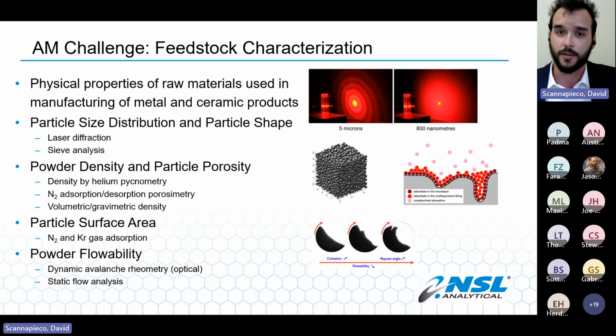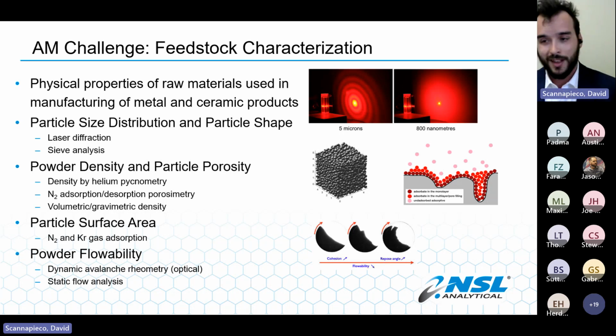And finally, one of the major differences for additive manufacturing is your feedstock characterization. You have powders, not ingots. Surface area is much higher, much easier to collect oxygen and expire the powder. It can go bad over time if it's not being used. In addition, when you put the powder through a build, that chemical formula might change somewhat. And in those cases, we need to be able to certify that recycled powder is going to be as effective as virgin powder. So again, this is a question of, do we need to chemical test after every build or after every 5 builds or 10 builds?